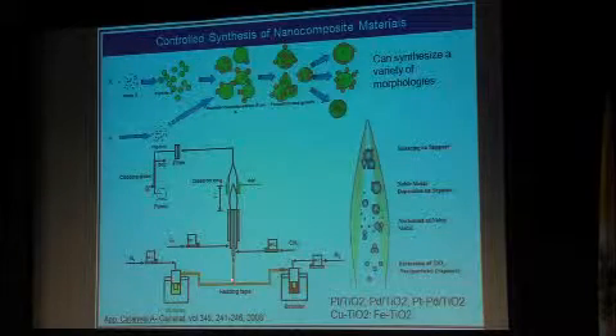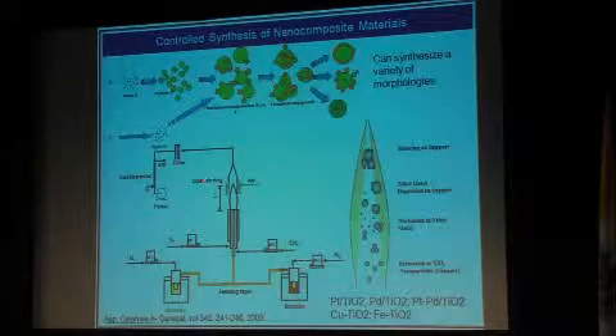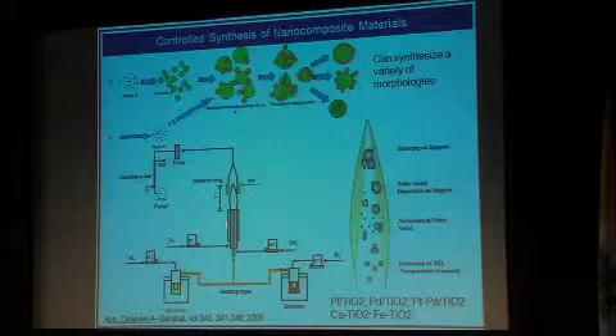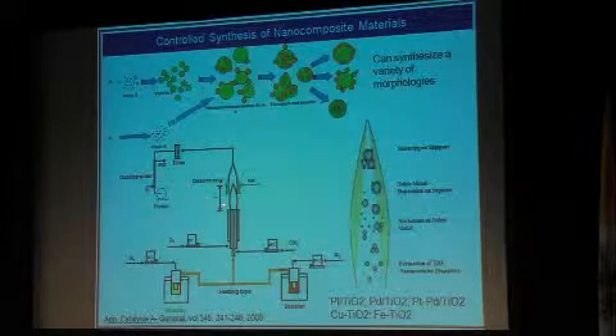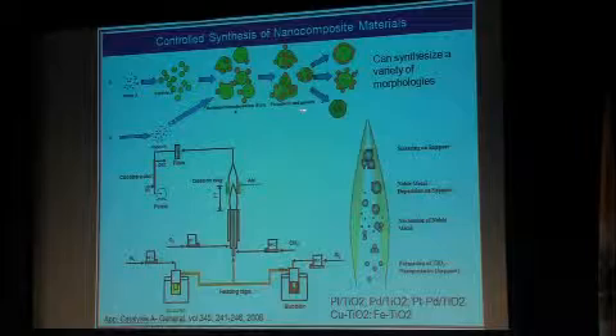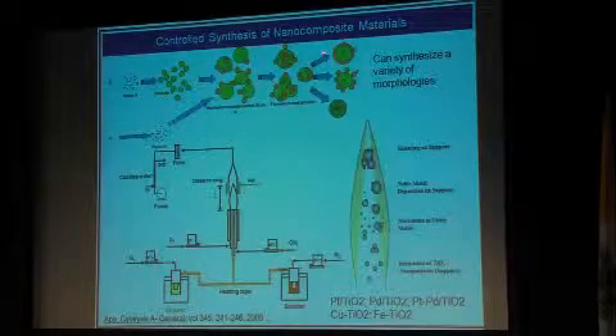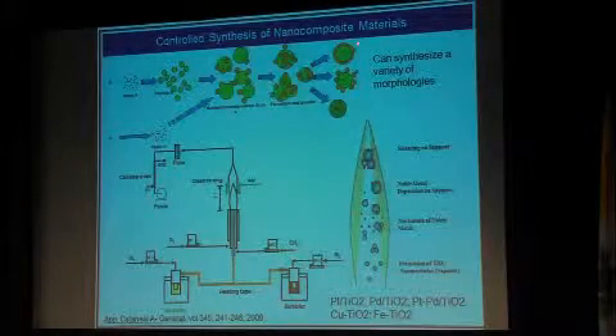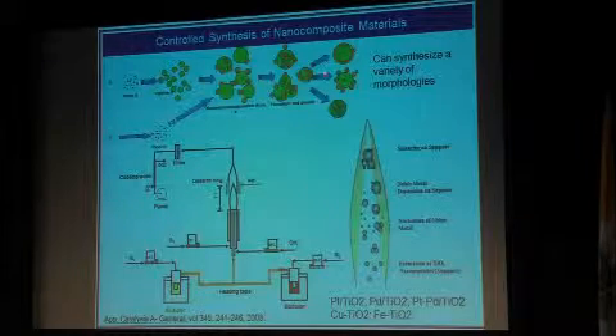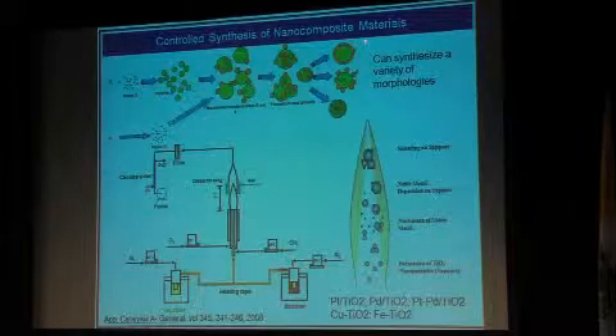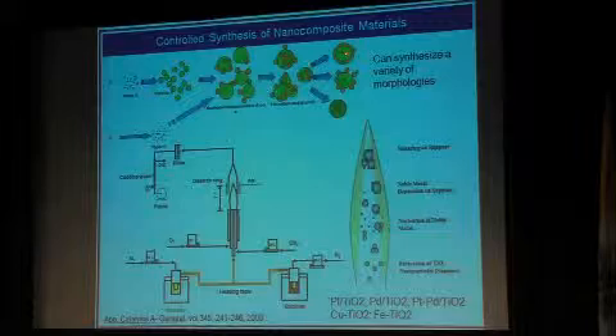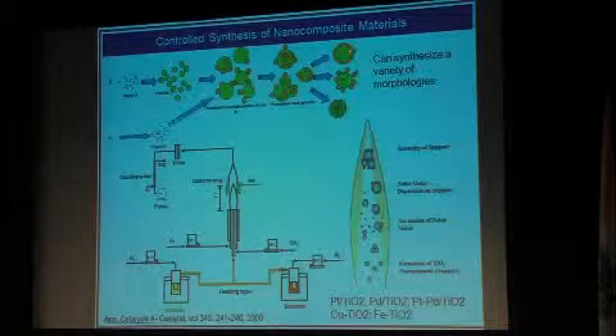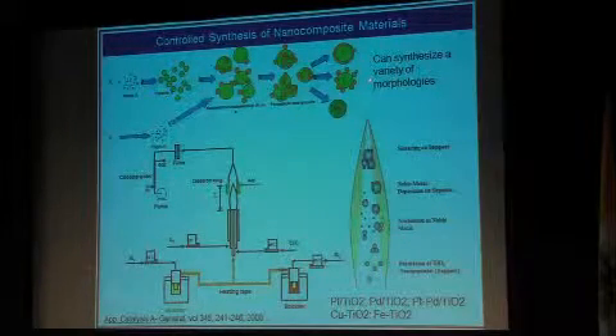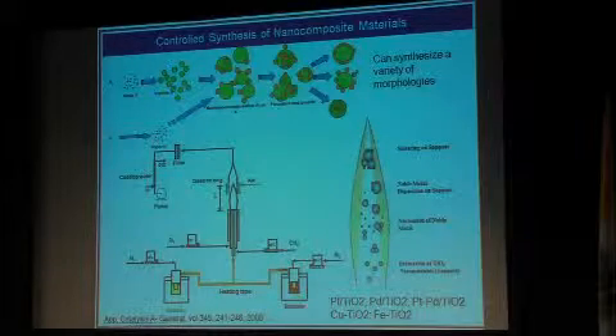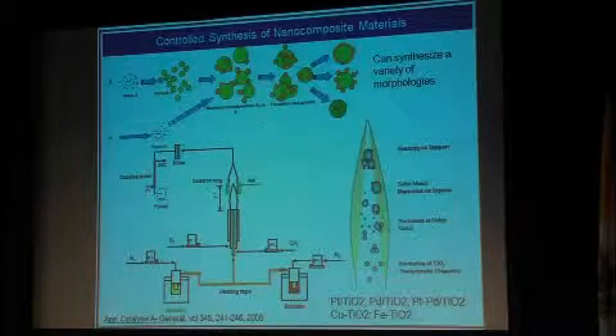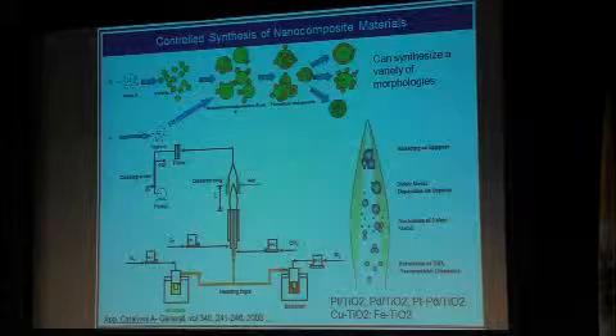The process is very similar. I'm not going to walk you through it now. I bring in 2 precursors. I want to understand in great detail now what happens, and here are different pathways shown. I could get a coating depending on the pathway I go through. With the second precursor, I could completely coat my TiO2 particle, or whatever particle I'm making as the base. I could get islands of copper, or I could get a homogeneous mix.